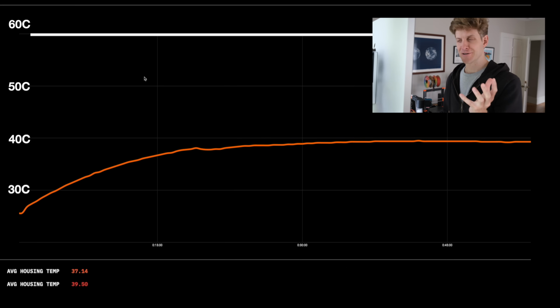So there's not that much here except just good results. On this graph, the top of the vertical axis is the glass transition temperature, so 60 degrees, and we're trying to stay as far below that as we possibly can, and looking at the data, we're way below that. The average housing temperature doesn't really matter.